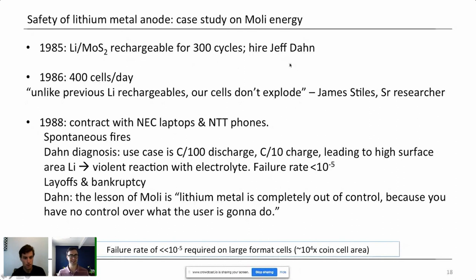So unfortunately, one of the lessons of Moli Energy is that they didn't do a good enough job in their accelerated life testing. But what you'll do is develop an accelerated life test and try and probe all of the corners of the use cases and even go beyond. So you'll stress test beyond what you'll allow the battery to do in the field. And you need to develop some sort of an algorithm or equation that you can extrapolate back from your accelerated life condition to a real world test condition.